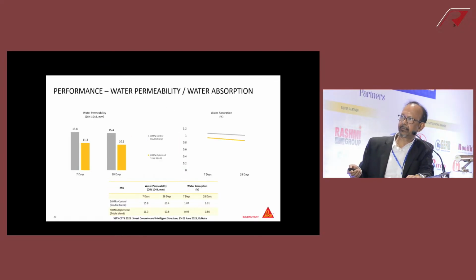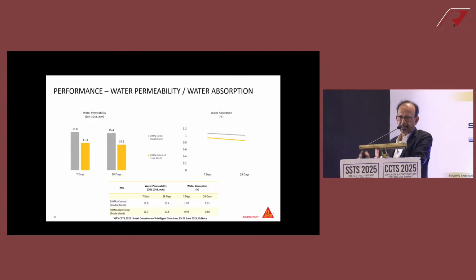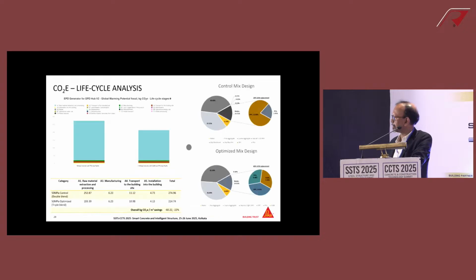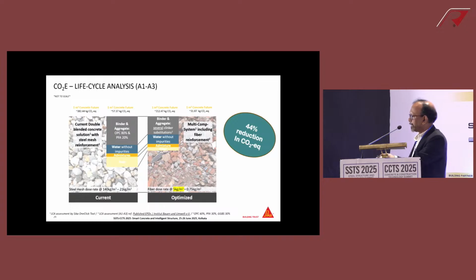And then you see the durability factor. This is very important. You see the triple blend in terms of 7 days and 28 days, and the water absorption, and the comparison with the control, which is double blend. Tremendous improvement. This is basic of concrete technology extended into high use of supplementary cementitious material. And you have a 44% CO2 savings. This is huge, especially for developers or anyone interested in LEED rating or green building.